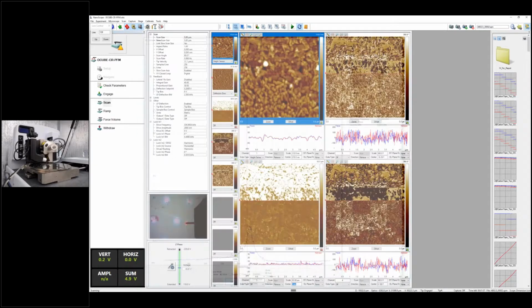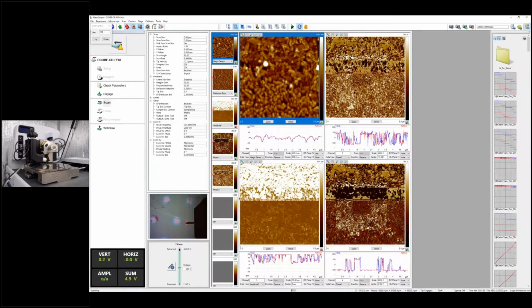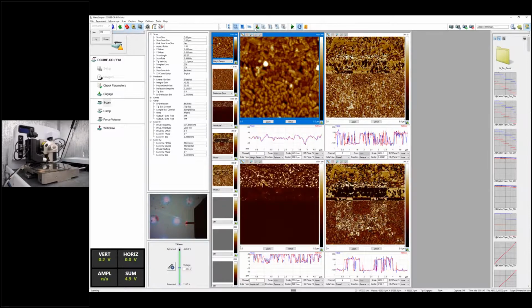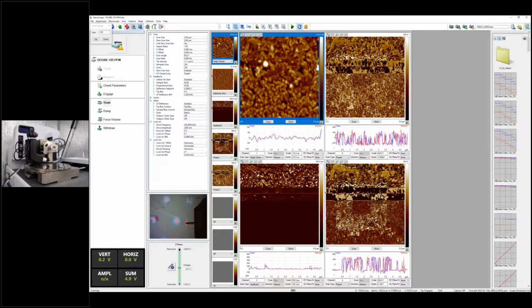And then let's come back to see the signal again. So now you see your amplitude is boosted quite a lot, and your phase is much cleaner because the signal to noise ratio for the amplitude is significantly improved. And the phase is actually derived by the lock-in amplifier based on the amplitude data. So now you can clearly see the distribution of grains in the phase channel, and somewhere you can also clearly see the domain walls. So this is the so-called contact resonance PFM.